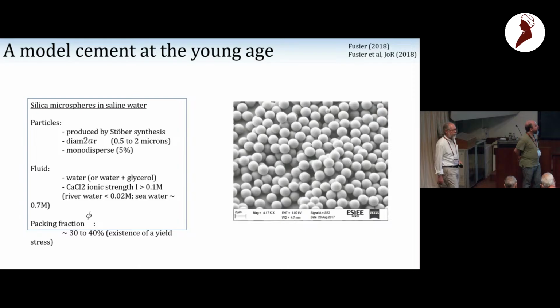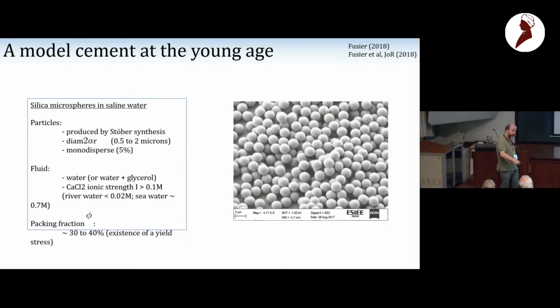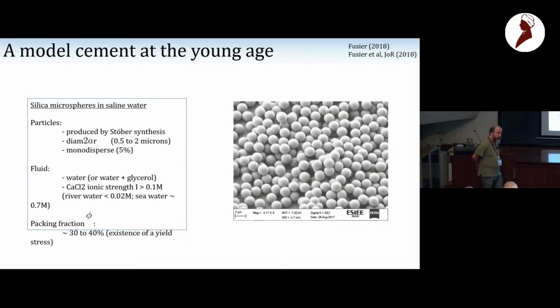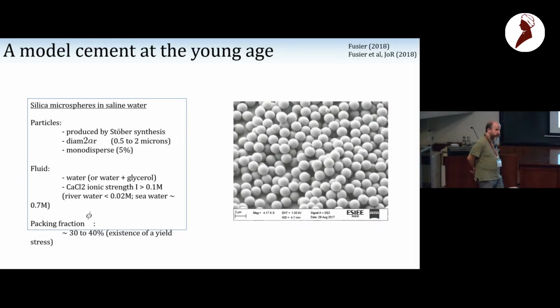Well, we can use a high shear rate, and we have shown that if you use a high shear rate, you can prepare your system repetitively, at least for a while, in the same initial state. But I agree with you that it's a kind of sintering process in a certain sense, that you form contacts and these contacts age, but you can rupture these contacts with flow. Is it answering your question?